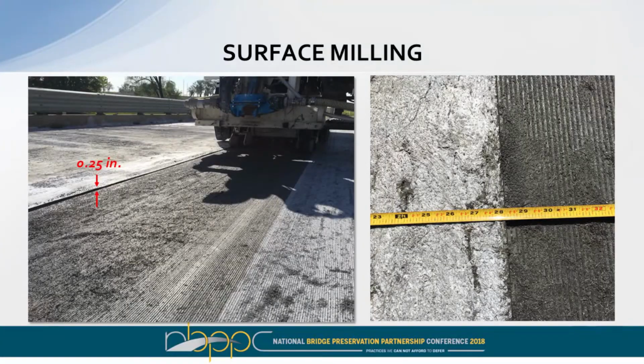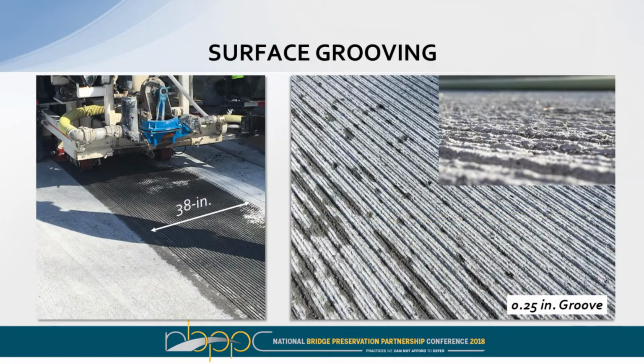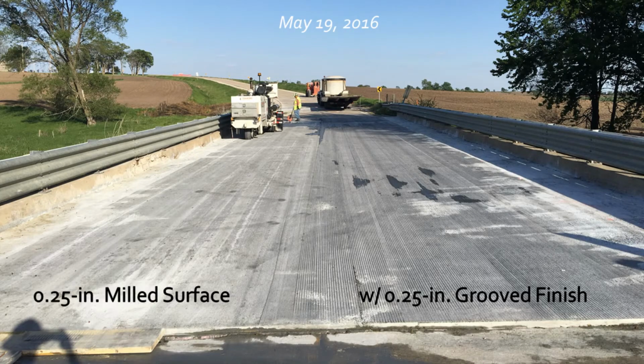And this is a couple photos showing that milling process here. Generally, we take off about 1/4 of an inch, and you can see on the right-hand side kind of that finished milled surface look in the fresh state there. And then some agencies, they'll also groove the deck. I've seen it in some agencies, some don't. Use the same equipment that you would use on conventional concrete to come through and do a grooving on this material. Kind of a shot of that Iowa project back in 2016. The left-hand side had been milled and the right-hand side had been grooved, and they're continuing to groove on the left-hand side with the machine there.